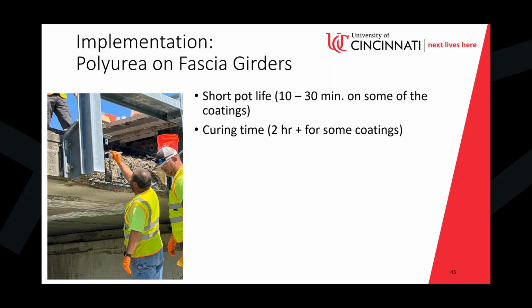And then curing time was an issue too. The curing time for one of these coatings took over 2 hours actually. And when you're just doing a small area like this and just focusing on this, you have to wait for that to cure before you can do the next coating. That's a lot of time just sitting around. Now, if you're applying it to multiple areas across a bridge, you could presumably be working in this area and move to another one. By the time you're back, it could have cured and you can move on to the next process. But there is some downtime definitely associated with waiting for the cure time.